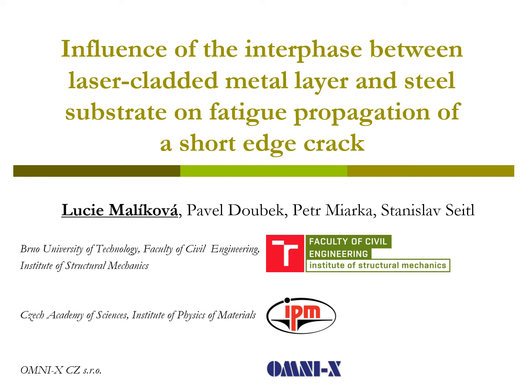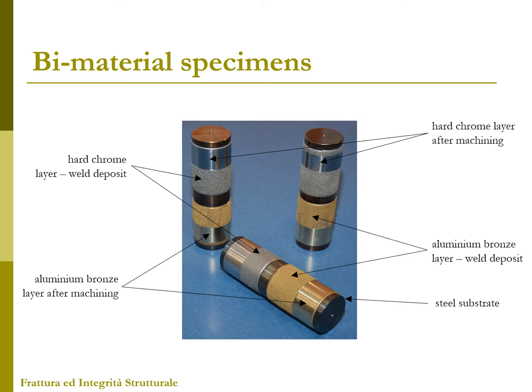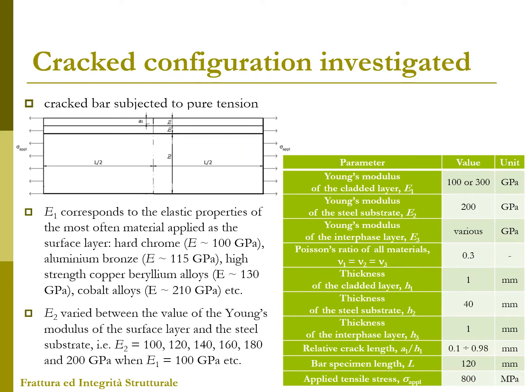In this work, the influence of the interface between the laser-cladded metal layer and steel substrate on fatigue propagation of a short edge crack is investigated. In the picture, you can see the real bimaterial specimens, where a thin metal layer is laser-cladded on a steel substrate. Here you can see the scheme of the specimen that was modeled.